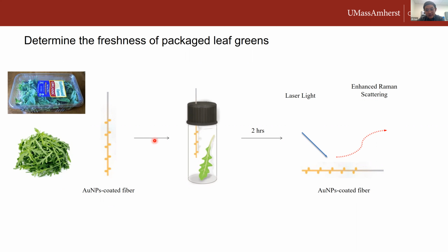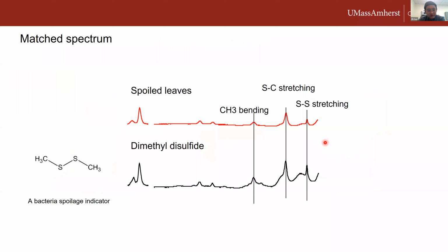In this case, we put these leaves in the refrigerator for different numbers of days. Then we collect the arugula leaves and put them in a small vial together with the SERS fiber. We incubate them for 2 hours, and then we collect the signal directly from the fiber. And in this case, we use dimethyl disulfide as the spoilage indicator.